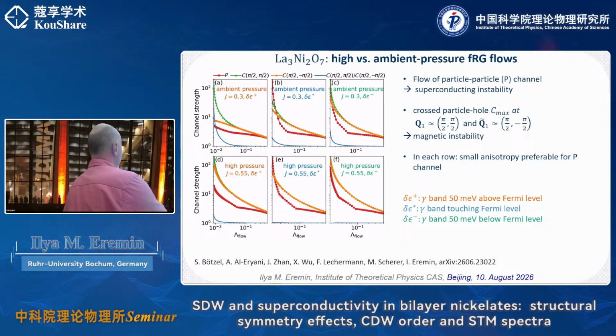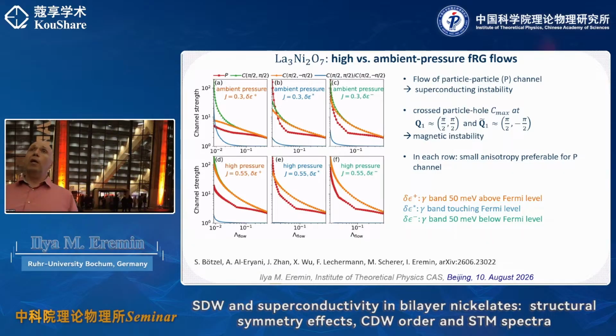And that is also seen as a function of the position of the gamma pocket. So effectively, magnetic frustration is an important aspect which needs to be present in order for superconductivity to win. Once you move to a tetragonal phase, magnetic frustration is large, fluctuations are big, and that does not allow long-range magnetic order to set in. Whereas in our orthorhombic system, it's easier to build up magnetism. However, in the tetragonal phase, superconductivity is taking over.